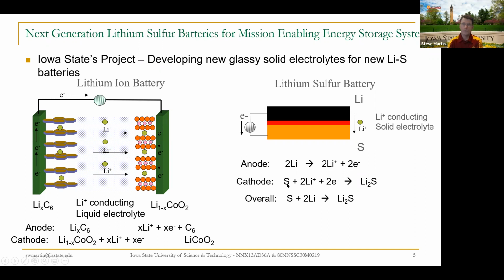And then, of course, when you are done with the battery and all the lithium sulfide has been formed, you just hook it up to a power plant, your AC circuit at home, and you drive this reaction backwards, separate the lithium from the lithium sulfide, produce lithium and produce sulfur, and you start all over and you drive to the grocery store or the next rover location on Mars as is needed.